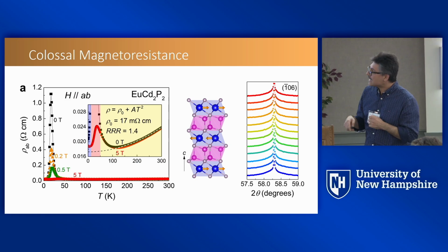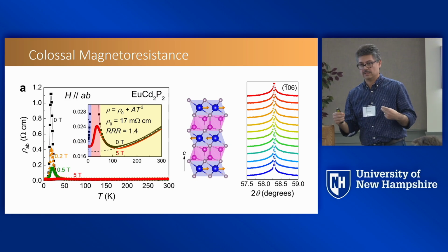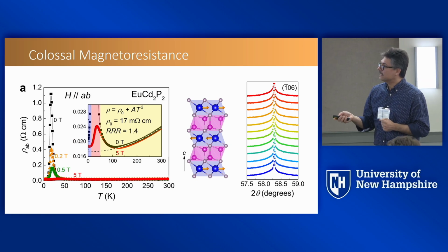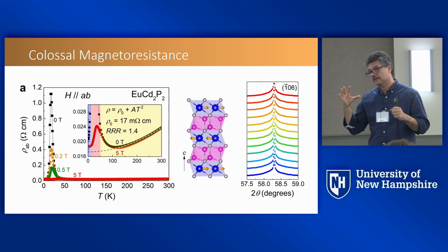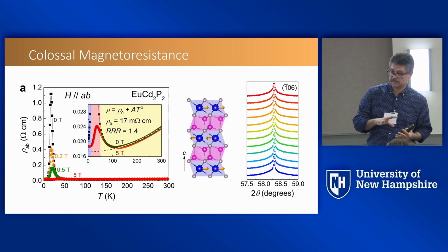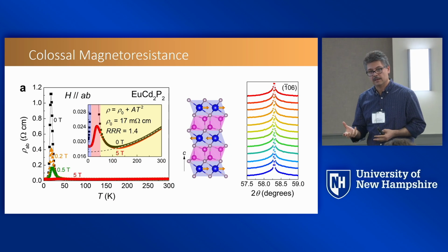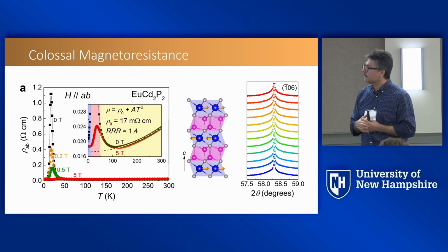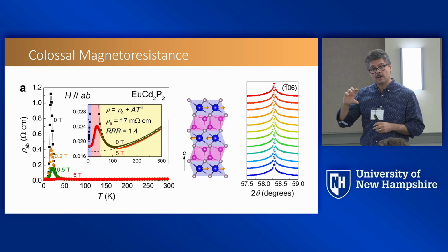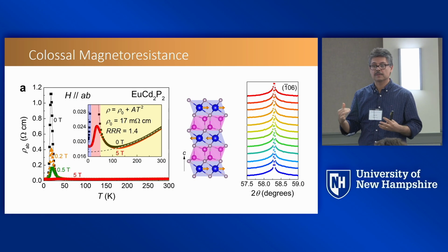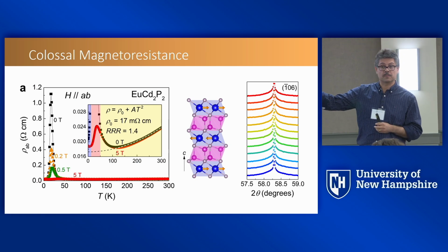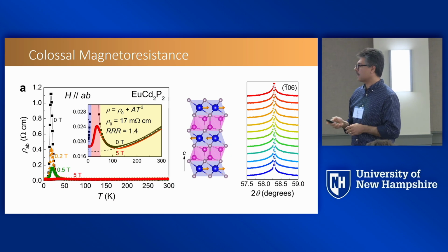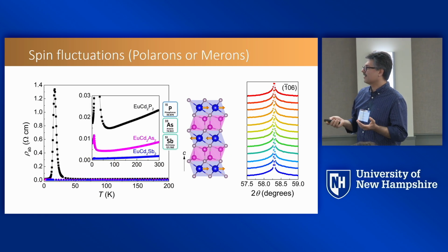And so it's happening in the regime of magnetic fluctuations, not in the regime of magnetic ordering. So this effect, whatever it is, seems to be related to strong magnetic fluctuations. But those fluctuations could be coherent. They could be, for example, polaronic fluctuations. One of my colleagues, Benedetta Flebus at Boston College, has another theory that this could be topological meron, anti-meron type fluctuations that can be suppressed sensitively with a magnetic field, and that's why this peak drops. There are competing scenarios, and as I said, I'm not going to have much time to go through it.